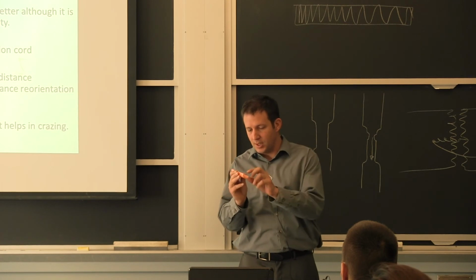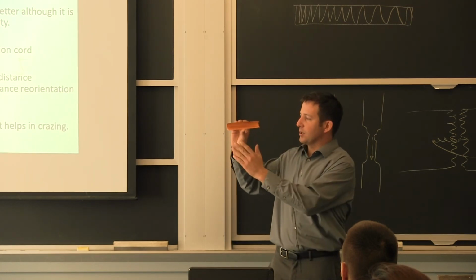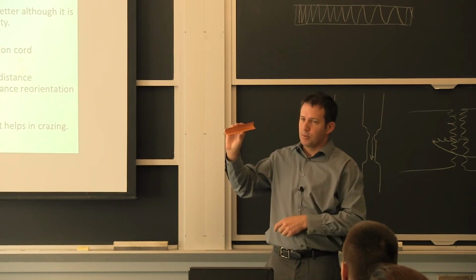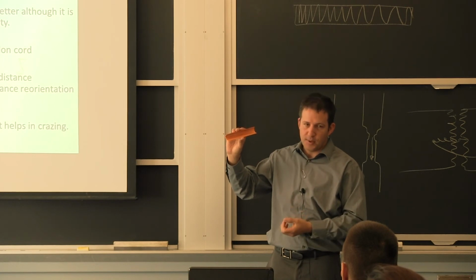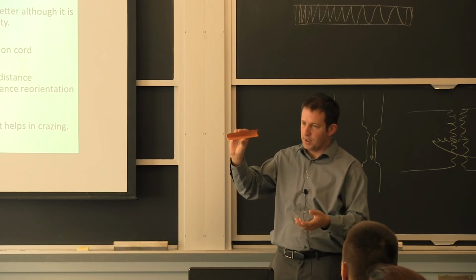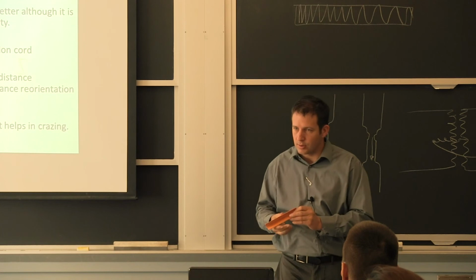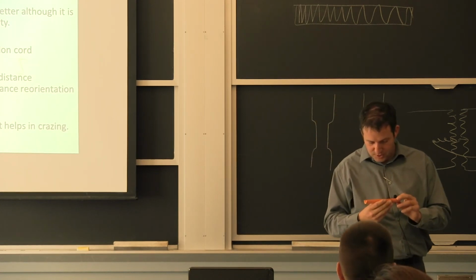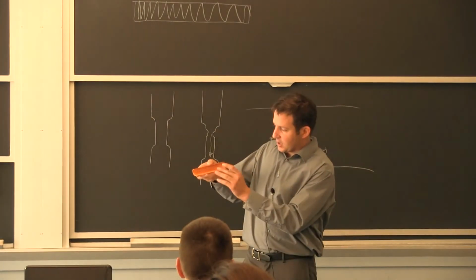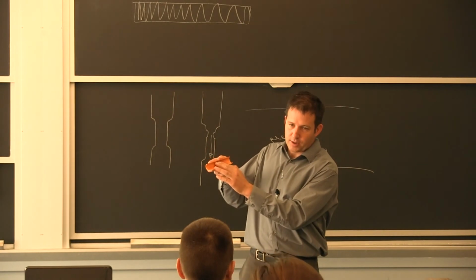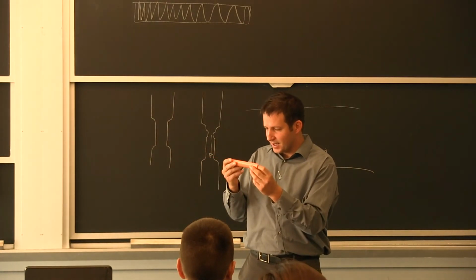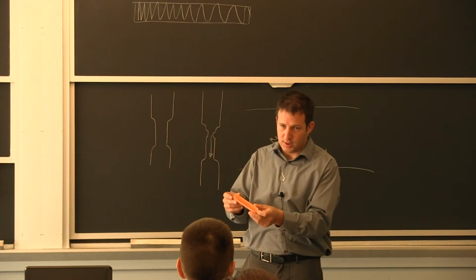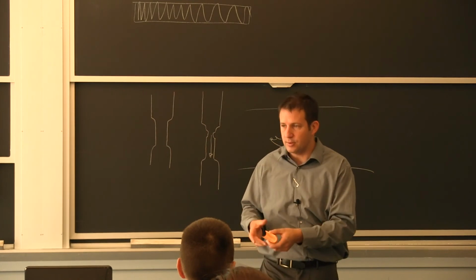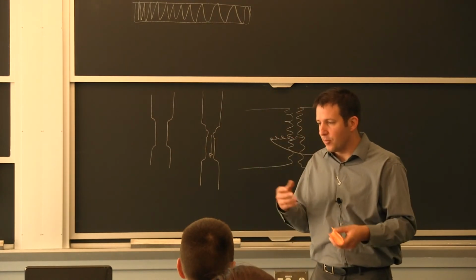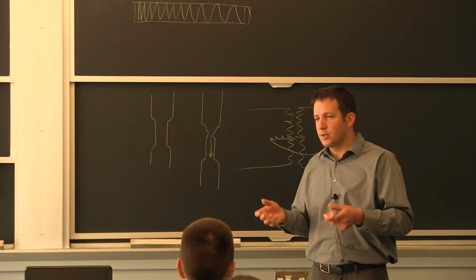So I'm showing here a cross section. These are high pressure. These will be used at 180 psi pressure, so 2 or 3 times what's used in regular water for sprinkler systems. And this side is a cut. This side is a slow fracture, and you can see that there was a residue inside the pipe that we associated with some form of oil introduction from fittings.